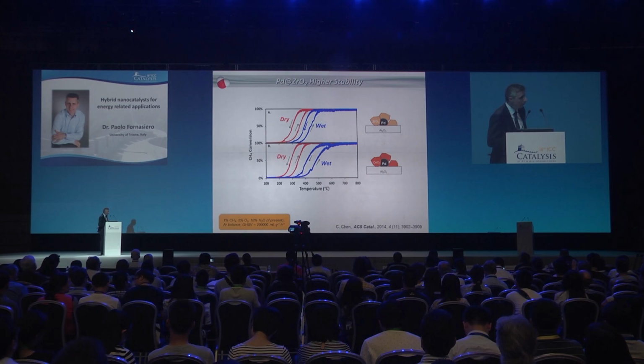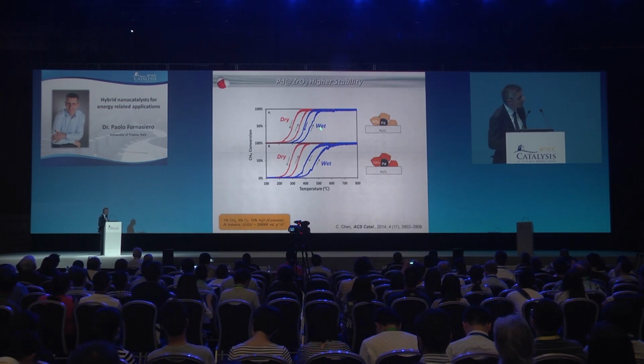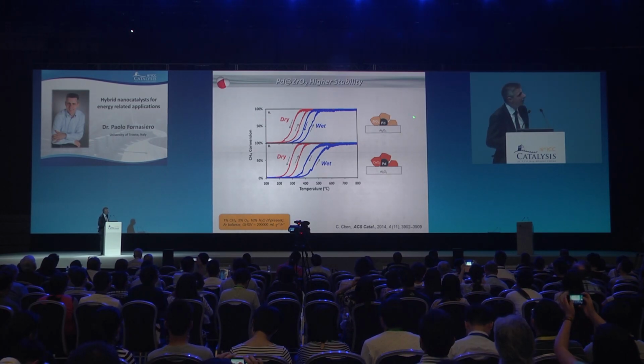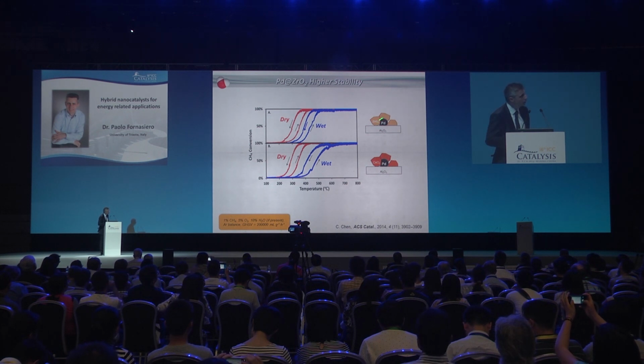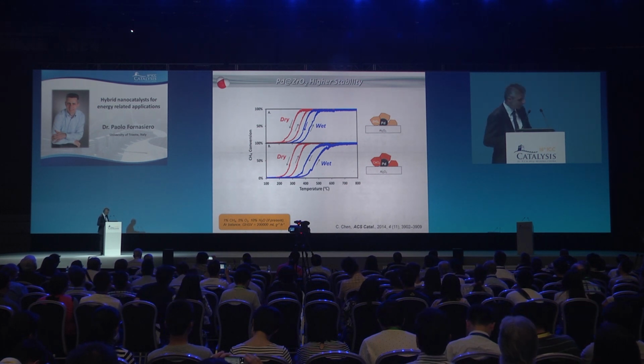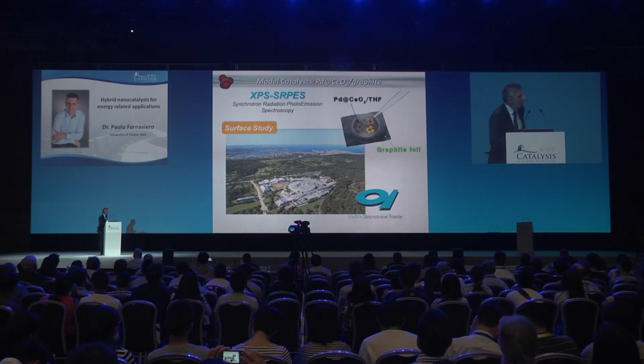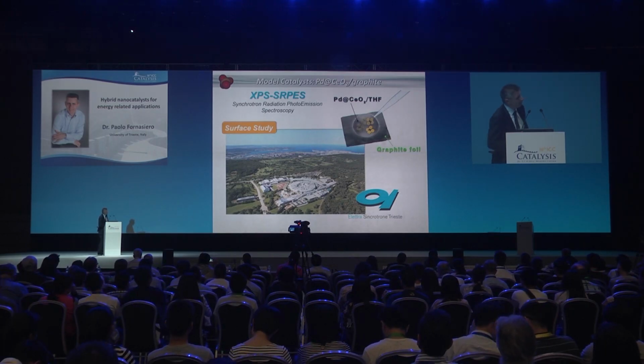And really, we end up with a catalyst which is less sensitive to the water effect, though still partially deactivated, and this is the zirconia-containing palladium system. So let's see the effect of the other poisoning gases.